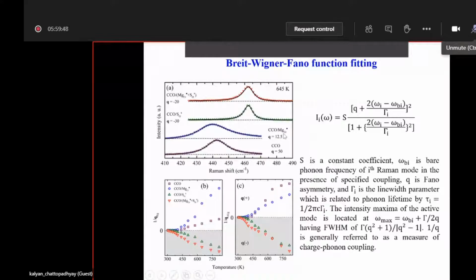For the magnesium doped sample, Q is 12.5. But interestingly, as soon as we introduce dopant at the anionic site, Q changes sign to -30, -20. This is more clearly presented when we plot 1/Q versus temperature. You see, as soon as there is dopant at the anionic site, the Q becomes negative.